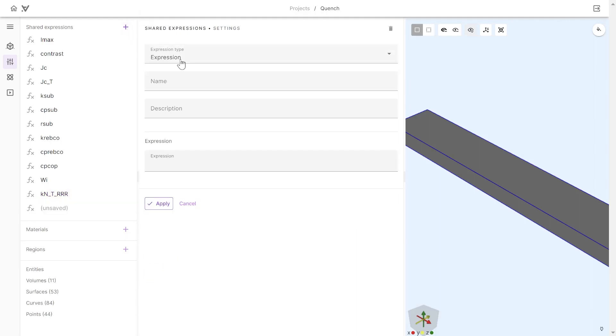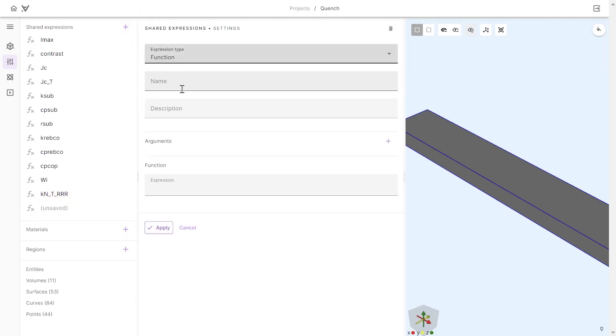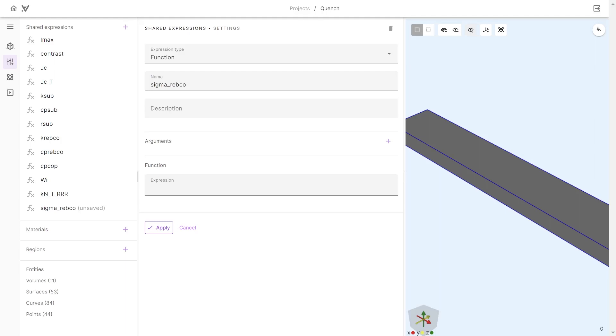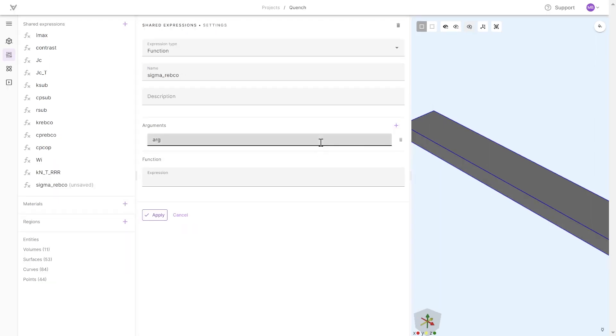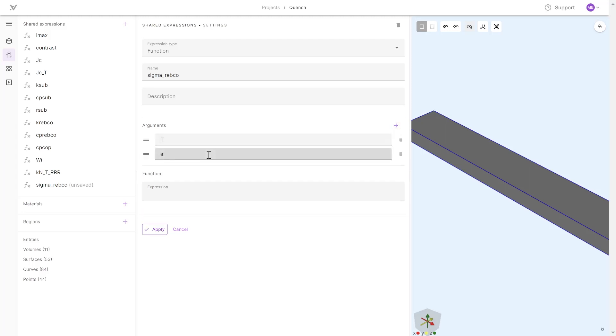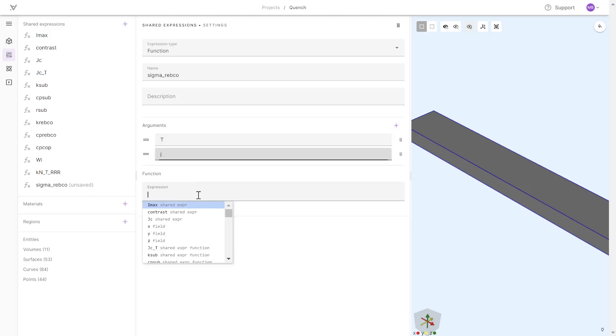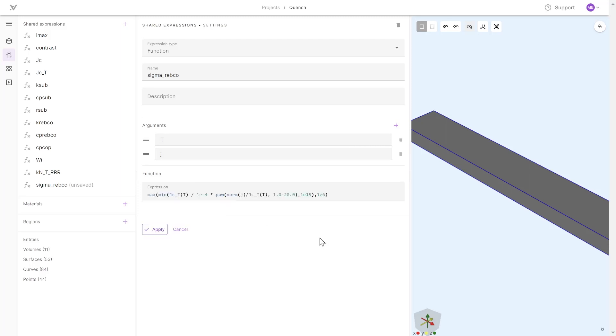As the last expression, I need to define the power law. The power law depends on two arguments: temperature and j, our current density. We use this power law definition calling the critical current density as a function depending on temperature, and we use bounds to avoid numerical issues.